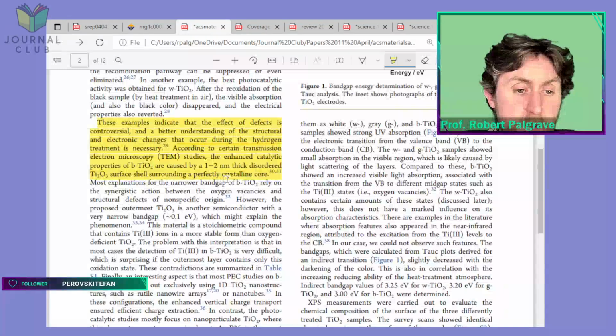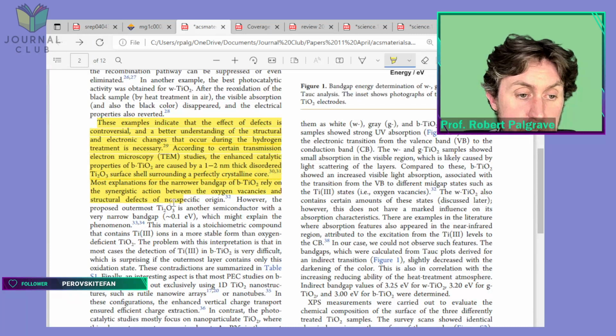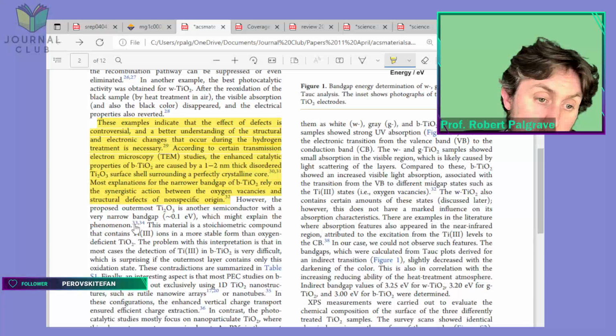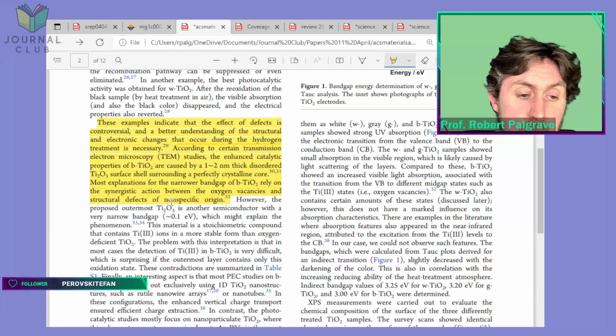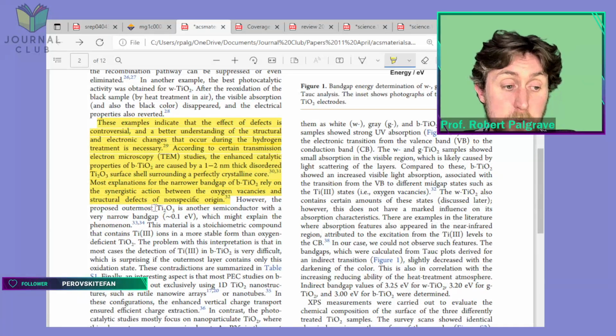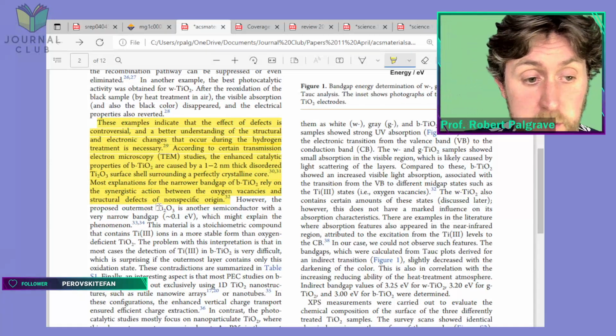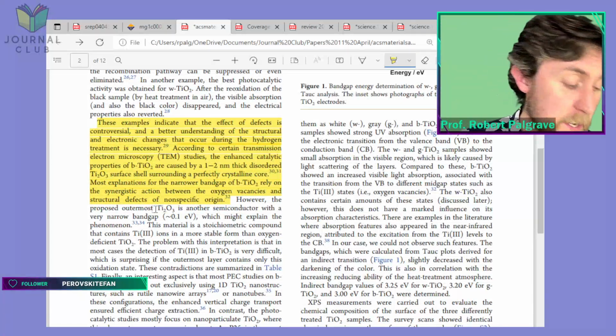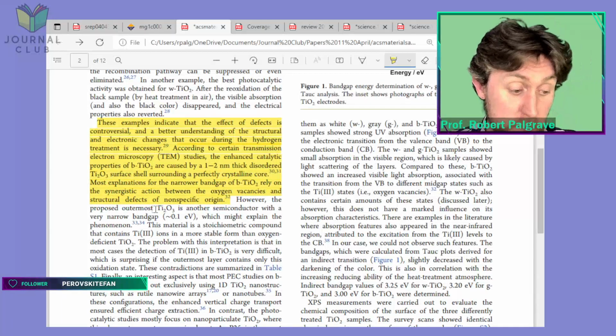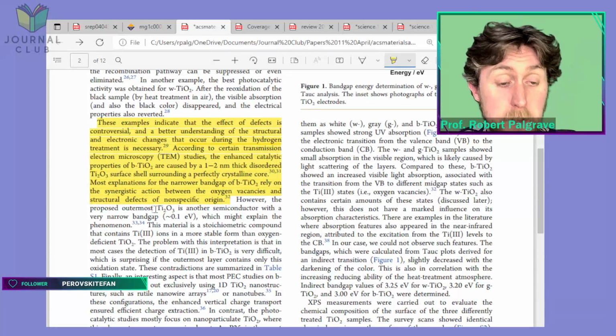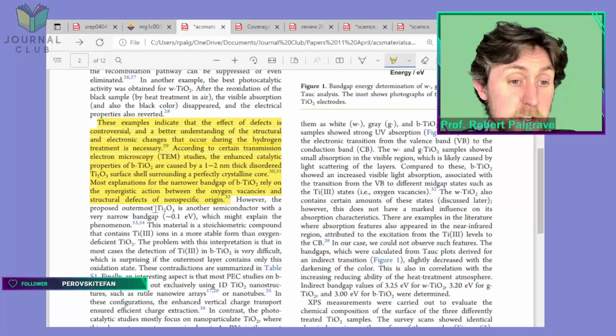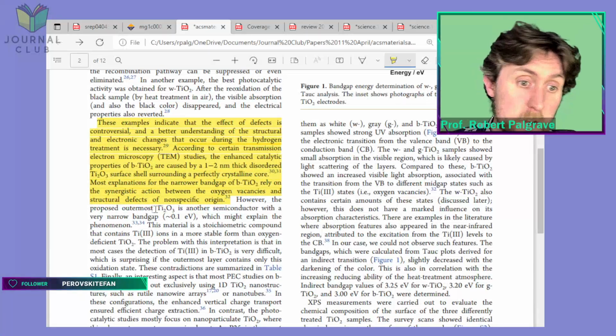Most explanations for the narrow band gap with black TiO2 rely on the synergistic action between the oxygen vacancies and structural defects of non-specific origin. However, the proposed outermost Ti2O3 is another semiconductor with a very narrow band gap, which might explain the phenomenon. Yeah, absolutely. So Ti2O3 is a different kind of titanium oxide. It's titanium 3+, as opposed to TiO2, which is titanium 4+. And because titanium 3+ has got one electron in its outer shell, it's a d1 oxide, as opposed to TiO2, which is a d0 oxide.